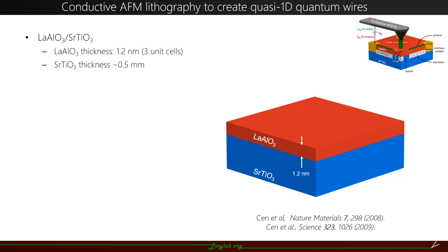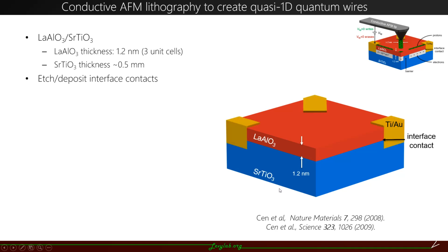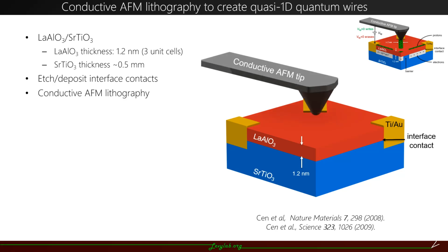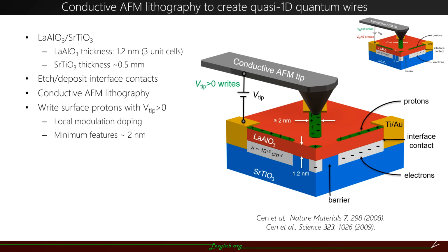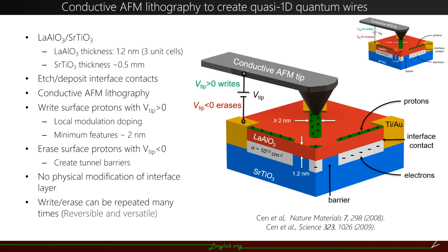First, we fabricate the sample so that the LAO thickness is only 3 unit cells. Then this interface is normally insulating. And then we fabricate metal electrodes to form direct electrical contact with the interface. And then we bring a conductive AFM tip to the contact. We apply a positive voltage to write the nanowires. The smallest size could be around 2 nanometers. And we apply a negative voltage to erase the nanowires. This writing and erasing process can be repeated many times, making this a very versatile platform.